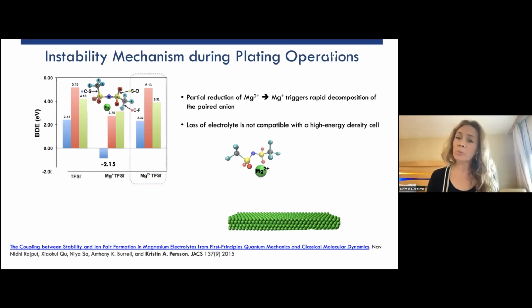And if we pair it with magnesium 2+, that's basically the contact ion pair in solution by itself. Again, this is a very stable TFSI. It doesn't decompose when it's exposed to magnesium 2+, which again agrees with our experimental impression of the system, that just because you dissolve the salt in solution or in the crystal, it doesn't decompose.